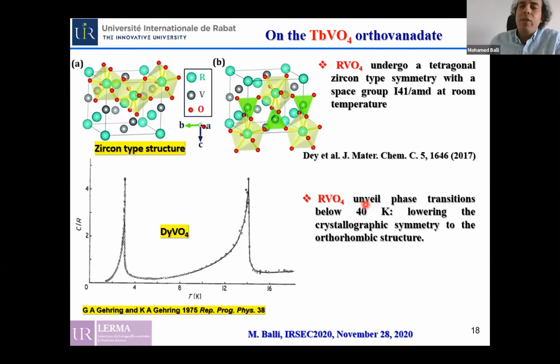When lowering the crystallographic symmetry from tetragonal to the orthorhombic structure, we observe a marked change in the crystal electrical field configuration. This change in the crystal electrical field configuration leads to large magnetization, usually along the A-axis, associated with a strong magnetic anisotropy and also magnetocaloric anisotropy.